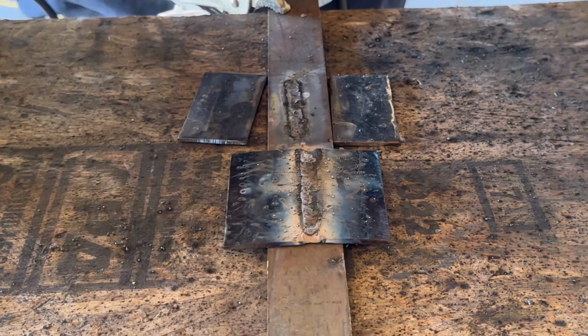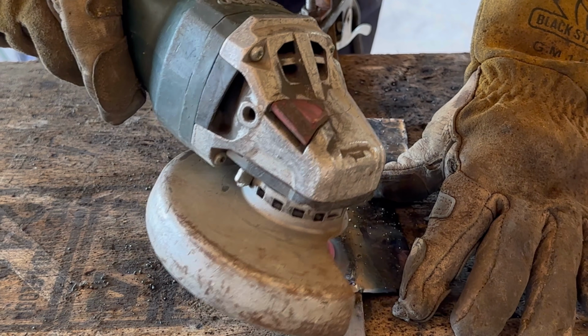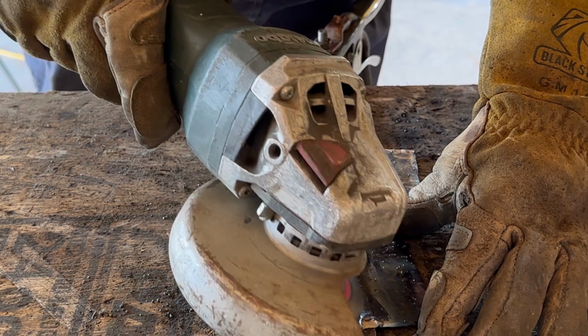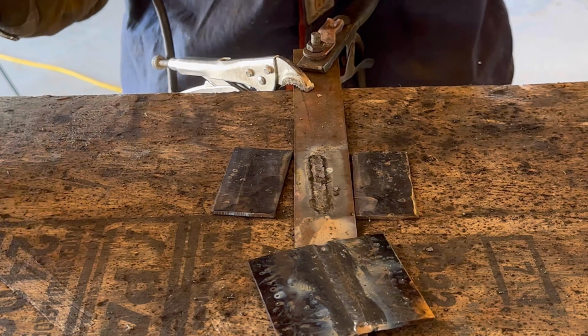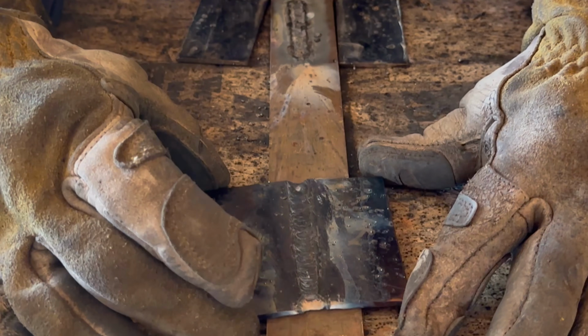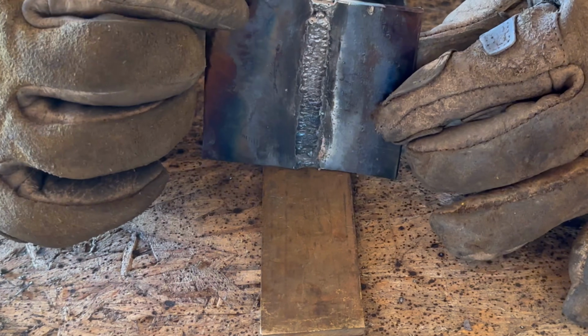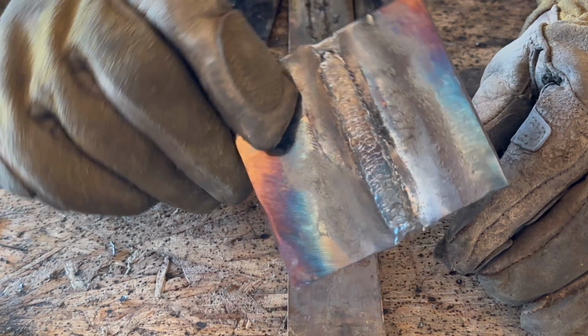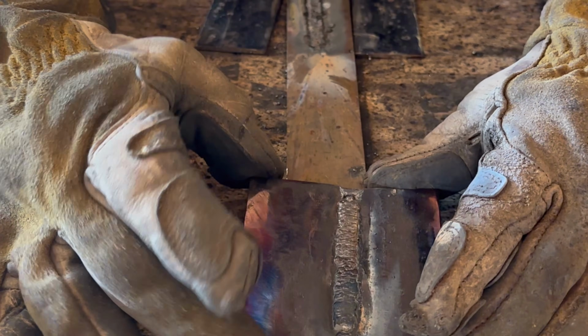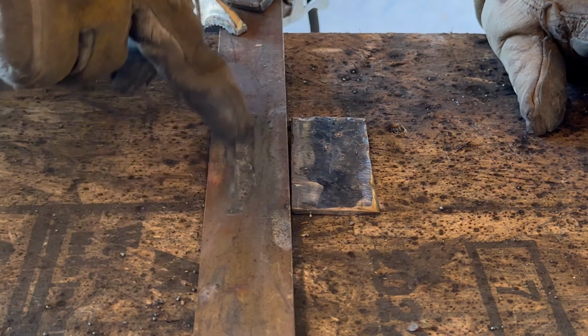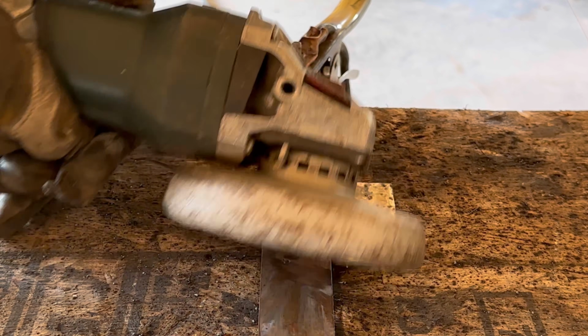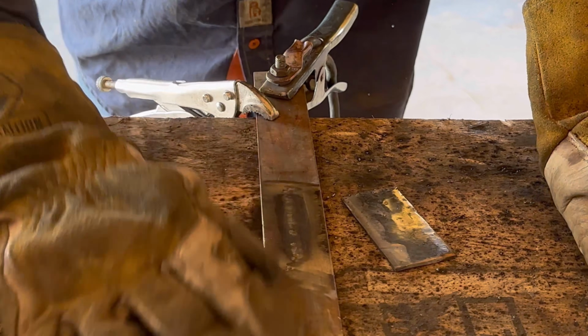Let's flip it over and get the flux off of that. So as you can see, we have a nice weld profile front and back. And if you look down it, you can see it's bumped up just a little bit on the bottom and on the top. So now these two pieces of metal are now one. So that's what you're looking for when you weld certain things, is a fully penetrating weld, which we were able to achieve with the use of a copper backing bar. And as you can see, the flux just stuck to the copper backing bar. I can go ahead and clean that up. And now this bar is ready to use again.